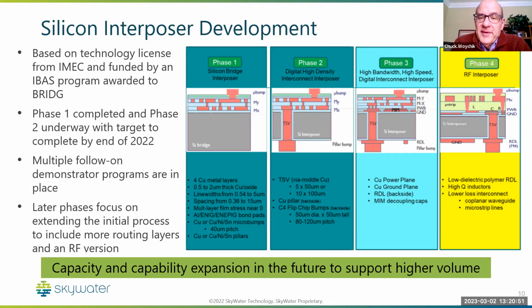This feeds into phase 3 interposer, which is shown in the schematic in this figure. And this gets into a more sophisticated buildup, more layers, but it will have a MIM decoupling capacitor embedded into the buildup structure, along with the same size TSV, but it will now have a backside bump and a simple RDL structure on the back. So this will be a more sophisticated silicon interposer. And the target qualification for this will be by the end of third quarter this year.